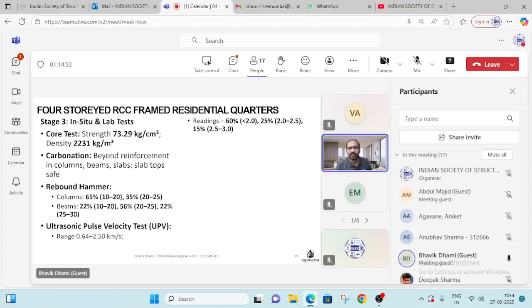In ultrasonic testing, you might see the range as 0.64 to 2.5. The majority of the velocity readings were less than 2. The majority of the readings were in the 60% criteria.